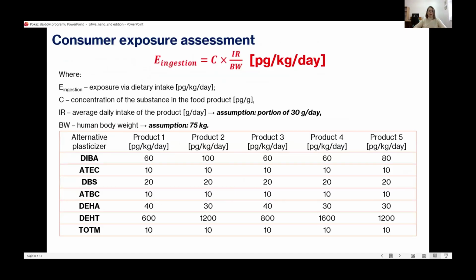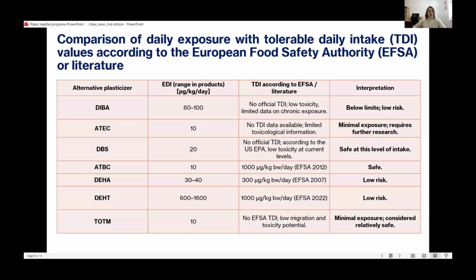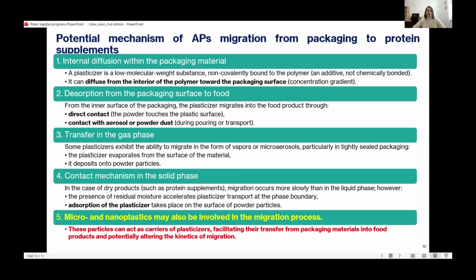To estimate consumer exposure, we assumed a daily portion of 30 grams of supplement and human body weight of 75 kilograms. Based on these assumptions, we calculated daily intake values and compared them with available toxicological thresholds. We compared estimated daily intakes, EDI, with tolerable daily intake, TDI, which was established by EFSA or reported in the literature. In most cases, exposure was well below these limits. In this case, migration can occur via direct contact of the powder with packaging, via aerosols generated during handling, or even via micro and nanoplastics acting as vectors.